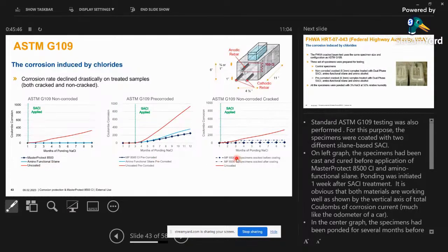So this basically is a dual phase surface applied corrosion inhibitor. It has been compared with amino functional silane, which has amine as a molecule. So these are different technologies of hydrophobic impregnators, and you will see that for non-corroded structures, both amine functional silane as well as dual phase corrosion inhibitor work almost the same. I mean, the effects are the same. So primarily to say that if it's a new structure, both technologies work almost the same.